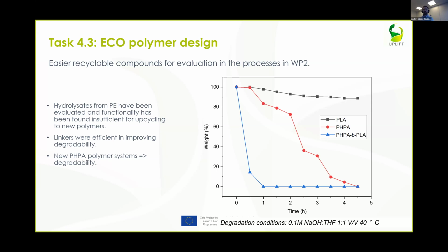And if we compare them in the plot that you can see here to PLA, we can see that PHPA degrades rapidly compared to PLA. And if we incorporate it together with PLA, we get an even more drastic effect in terms of weight loss for these systems. So this is a very attractive system for obtaining a higher degradability.